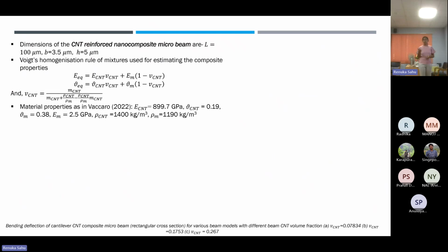This theory has then been applied to a CNT-reinforced nano-composite microbeam, whose geometric parameters are as follows. We used Voigt's homogenization rule of mixtures for estimating the composite properties, and the material properties were taken from Vaccaro.